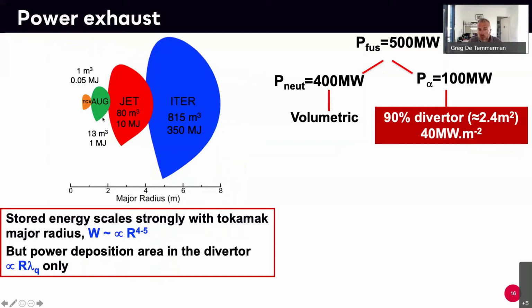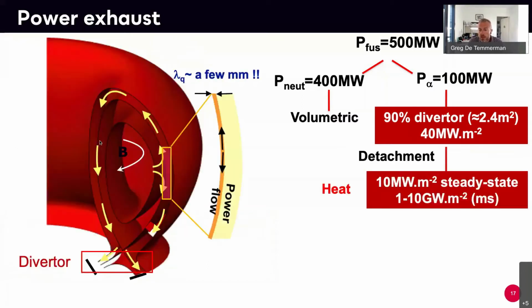But the stored energy, so the energy I have to dissipate, actually scales with a power of typically 4 to 5 to the radius. So as I make those machines bigger, and ITER is much bigger than the machines we had before, then the amount of energy we get is much higher, which is good, but I don't have so much surface area on which to deposit them. Now, we can do some tricks in trying to extinguish a bit of the plasma before it comes to the surface, but we still have to deal with extremely high heat fluxes,